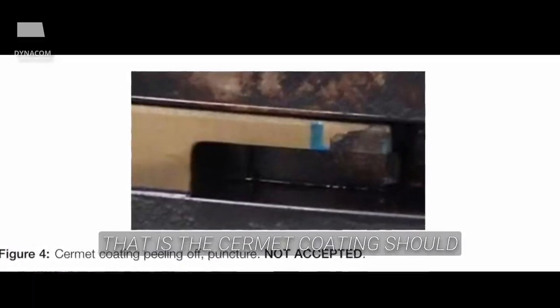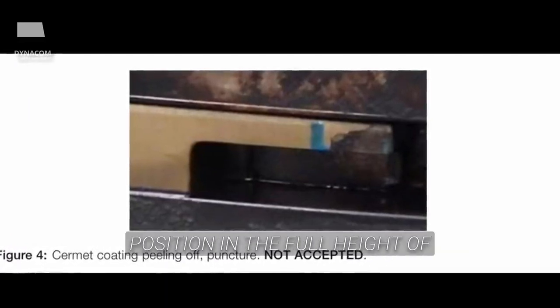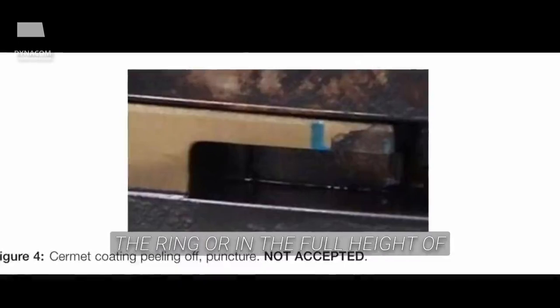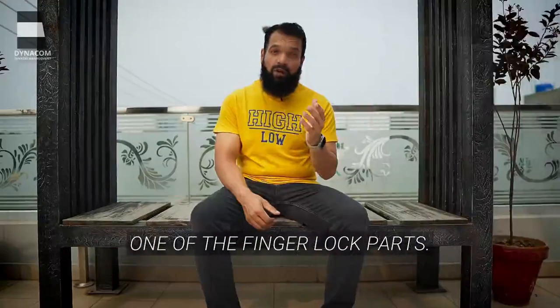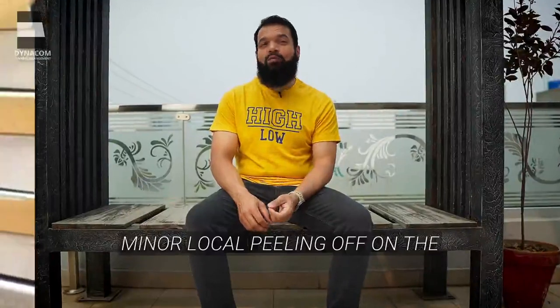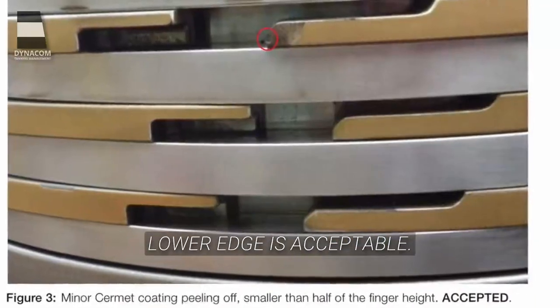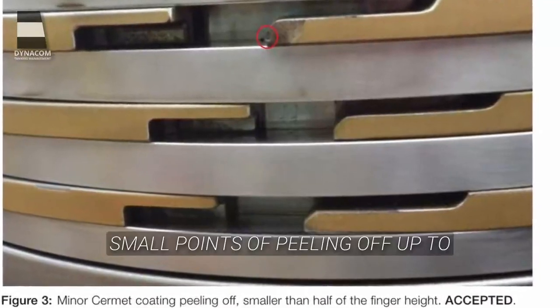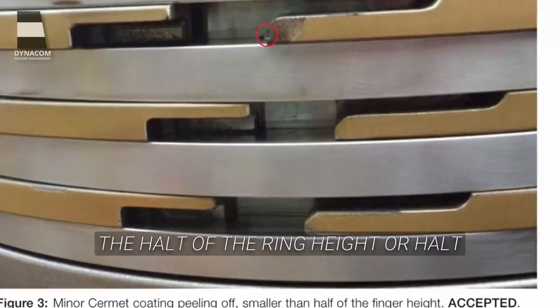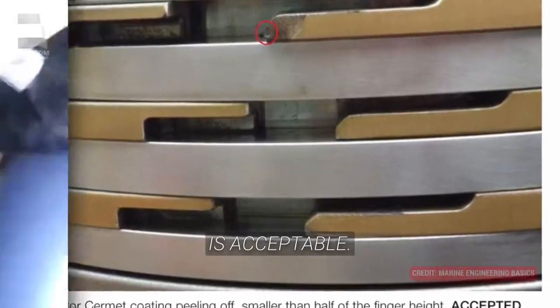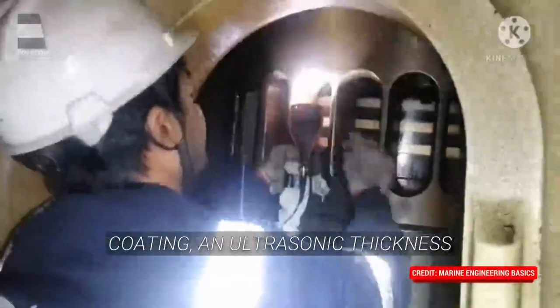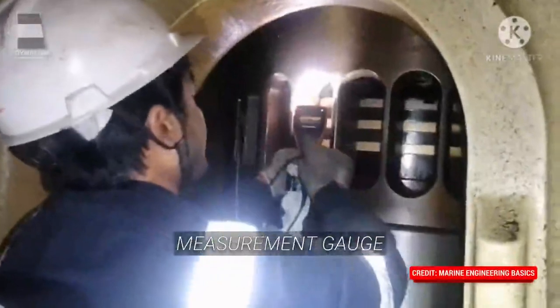That is, the cermet coating should not peel off in any position in the full height of the ring or in the full height of one of the finger lock parts. Minor local peeling off on the piston ring upper or lower edge is acceptable. Small points of peeling off up to the half of the ring height or half of the finger height is acceptable. To measure the thickness of cermet coating, an ultrasonic thickness measurement gauge is used.